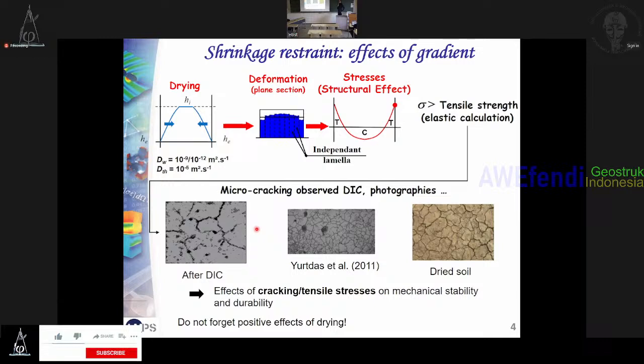So when you dry the specimen, you will dry at the beginning the surface of the specimen. So you will have more drying shrinkage in the surface than in the core. So you are restraining shrinkage of the surface. So in order to restrain the shrinkage, you should induce tensile stress. So we will find that you will have tensile stress in the surface and you have self-equilibration. So it is self-equilibrated by compressive stress in the core of the specimen.